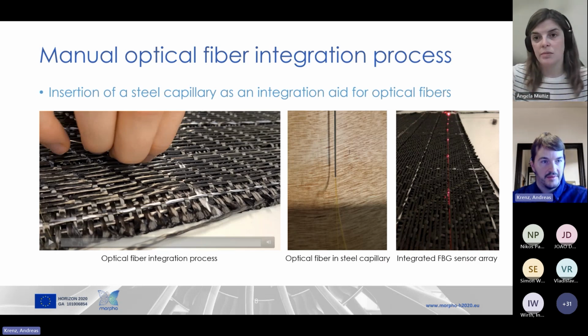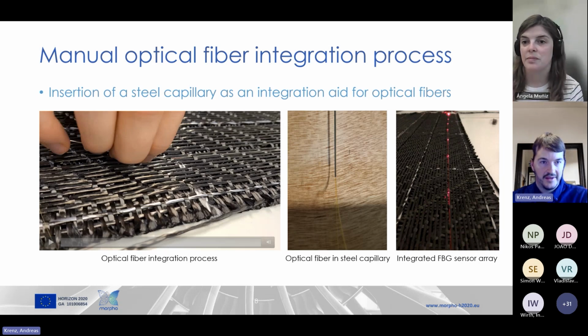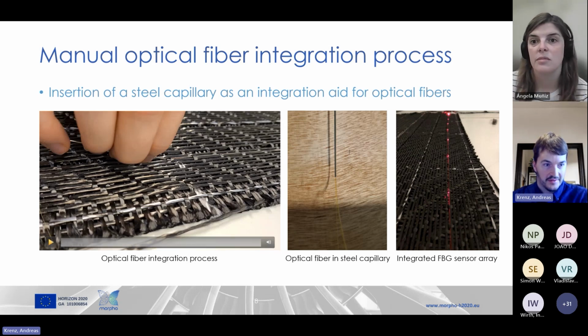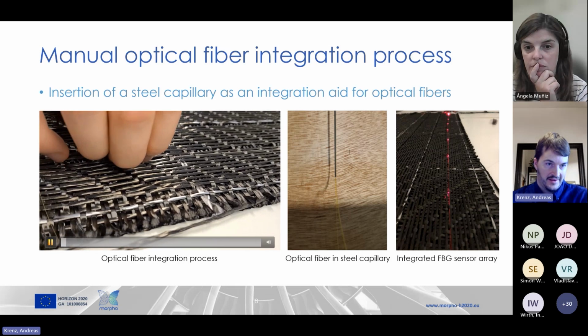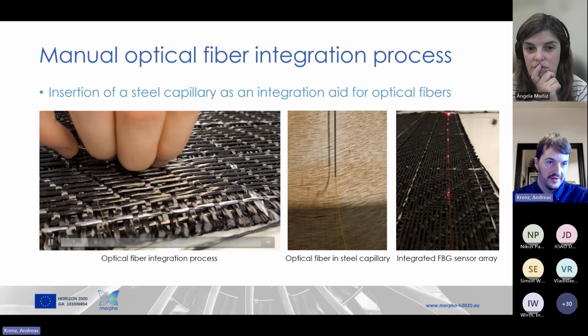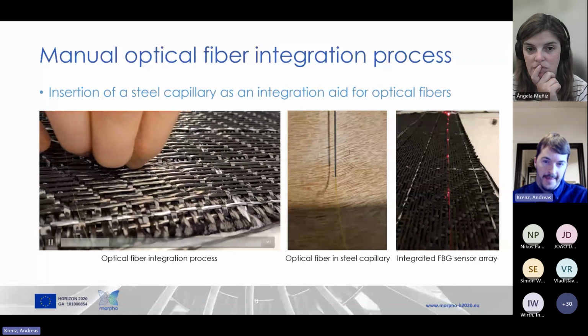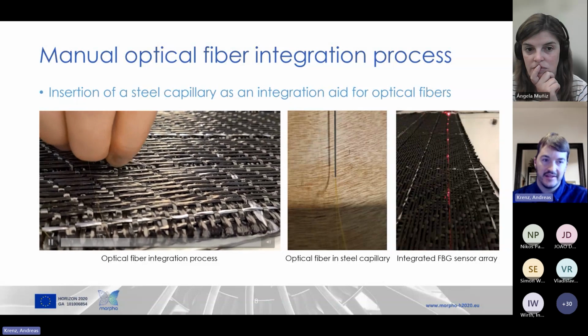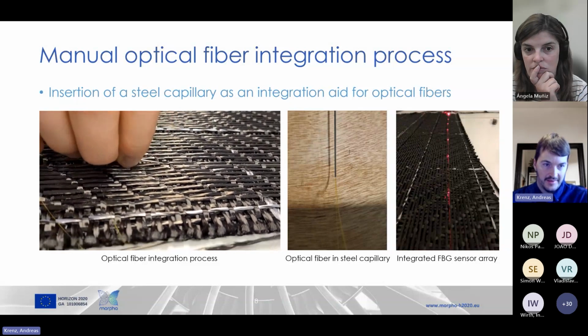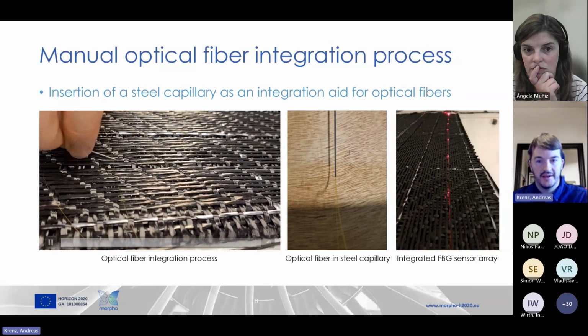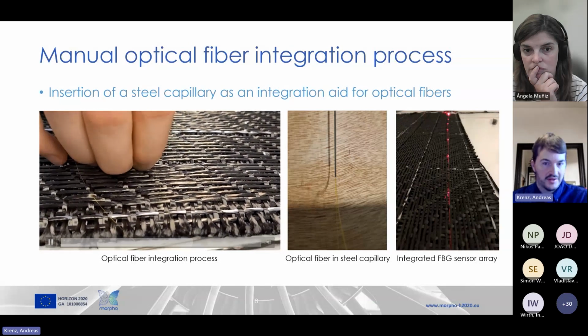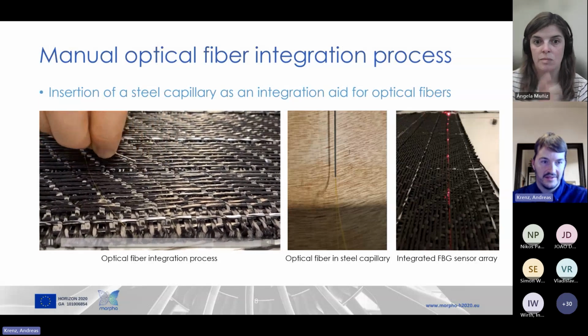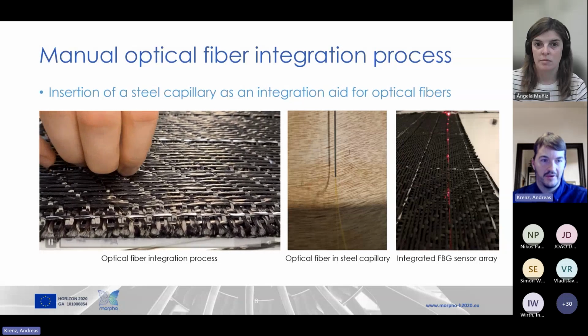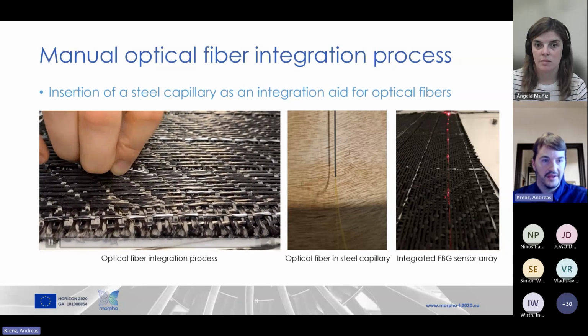And as mentioned, it was performed by the insertion of a steel capillary as an aid for integrating the fibers. And this video shows the procedure of embedding into the outer surface area of the preform. And there you can see the manual way to insert the steel capillary. And after this steel capillary was embedded, the optical fibers were inserted into the steel capillary, and then the capillary was pulled out again to the back side, and so the glass fiber takes its place in the preform. So this was the way we performed the integration.